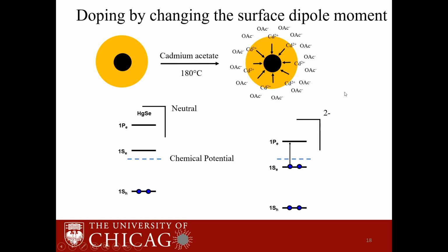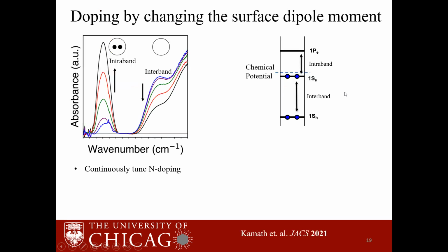When we treat our quantum dots with cadmium acetate, cadmium ions like to bind strongly to the quantum dot surface. So we see a layer of cadmium ions on the quantum dot surface, and a layer of negative acetate ions will be in the solution as counter ions. This geometry leads to an electric field that is pointing towards the center of the quantum dot. And the electric field that is produced by this geometry will bring down the energy levels of the quantum dot states, so that if the electric field is high enough, then the conduction band state can go below the environmental chemical potential, and we observe a filling of the conduction band. And this is a very convenient way to dope the quantum dots, because just by changing the amount of cadmium acetate, we can obtain quantum dots with any given value of doping.